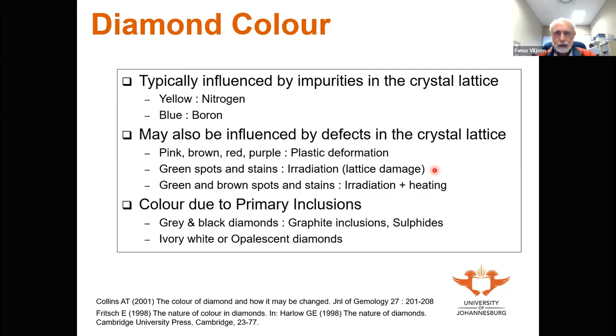Diamonds that are weathered out of the kimberlite and end up in the alluvial environment may be affected by irradiation when they are in touching contact with radioactive minerals. And in that instance, you get lattice damage. So it is not just surface coating, it is actually lattice damage that penetrates into the diamond for a couple of microns. And in that case, you get green spots and stains. It's important to emphasize that these green spots and stains cannot be removed through acid boiling, for example. They are there, and it's a permanent form of surface damage.